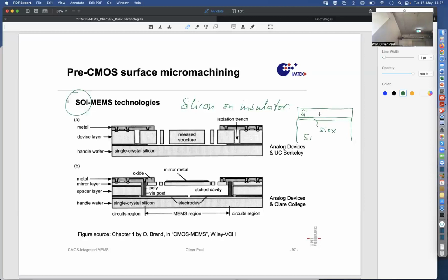Then you need to be precise in your polishing. Or you do an implantation of oxygen deep into the silicon, a high energy oxygen implantation, which is then annealed at high temperature. So the oxygen condenses with silicon to an oxide layer and retreats from the surrounding silicon. So you have the original silicon on both sides and an oxide layer between.